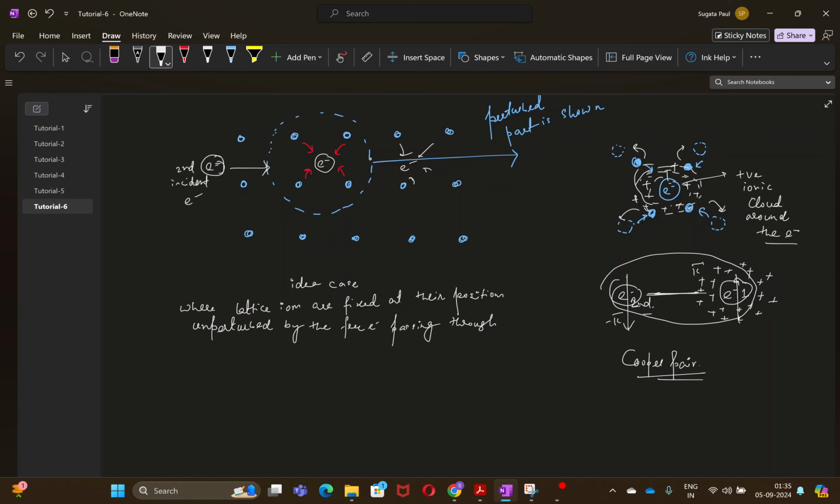So basically, the phonon is the reason why two electrons are weakly coupled to each other despite being of equal charges. So there should be Coulomb repulsion, right? Both electrons are negative charges, so they should not attract each other, but instead there should be strong repulsion between the equal charges by Coulomb's repulsion. But instead of that, there is still a pairing happening between these two electrons, only because these phonons are in the picture. So this lattice is kind of acting as an indirect glue between the two electrons to form a Cooper pair.